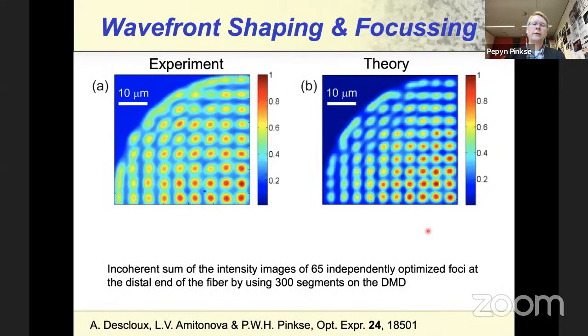You can make these foci at different positions. And this is the experiment where we put, it's actually a composite image, where we put foci at different positions. In the center, it's nicely round. If you go more toward the edge, you see that there are some distortions, which you also understand theoretically, and basically has to do with the mode structure of the fiber.